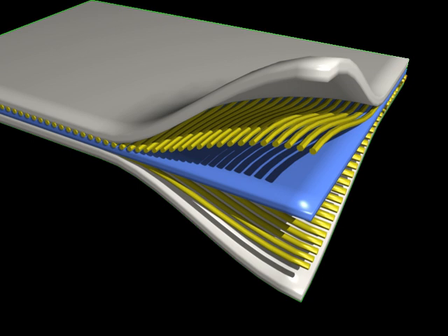When a fiber has some angle of misorientation theta, several fracture modes are possible. For small values of theta, the stress required to initiate fracture is increased by a factor of cos^-2 theta due to the increased cross-sectional area A/cos theta of the fiber and reduced force F cos theta experienced by the fiber, leading to a composite tensile strength of sigma_parallel / cos^2 theta, where sigma_parallel is the tensile strength of the composite with fibers aligned parallel with the applied force.